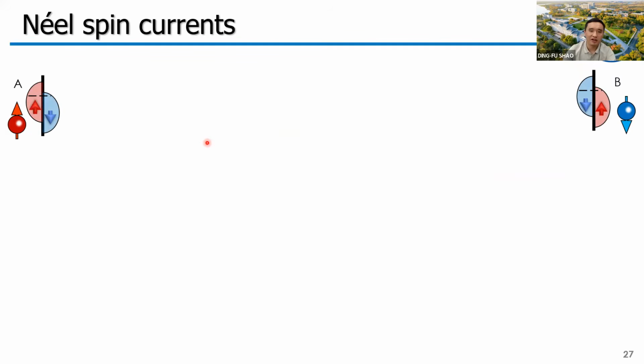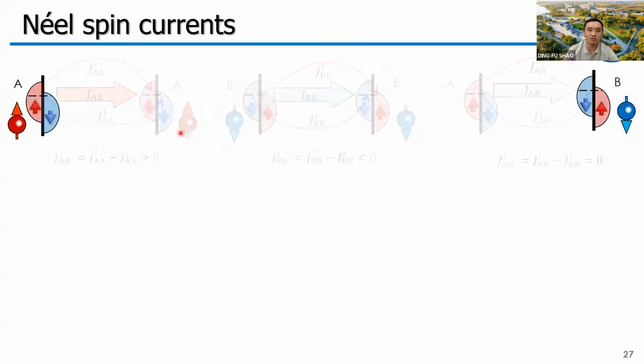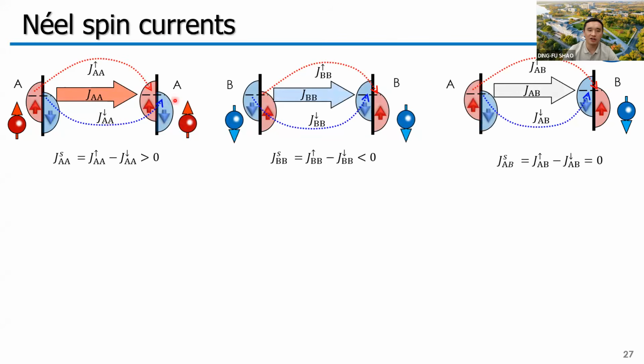Here, I consider a very simple antiferromagnetic metal with only two magnetic atoms, A and B. A and B are the same element, but their moments are antiparallel. So if we apply an electric field to this antiferromagnetic metal, the generated longitudinal current can be decomposed into the intra-sublattice currents JAA and JBB, or the inter-sublattice current JAB.